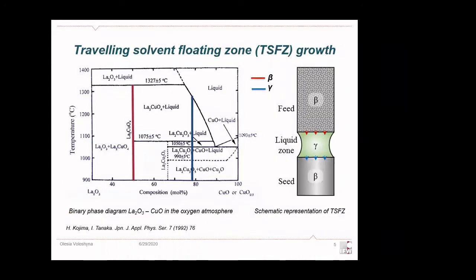And as you can see on a binary diagram representing the state of the binary system depending on the ratio, on the X scale, and temperature, the lanthanum cuprate melts with decomposition. And obviously this material in single crystal form cannot be obtained with a classical melting technique. In such a case, we use the so-called traveling solvent floating zone